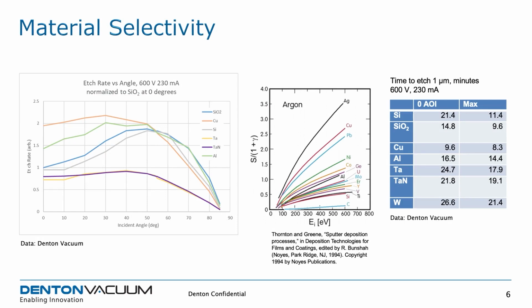So next, I'm going to talk a little bit about material selectivity. If you talk about ion etching, a lot of people are familiar with reactive ion etching. In that case, it's very much a chemical process where the etch rate can be completely different for different materials depending on your gas chemistry. You can have etch selectivity of 10 to 1 or 20 to 1 is common, or you can even push it higher depending on your materials and gases you're using.